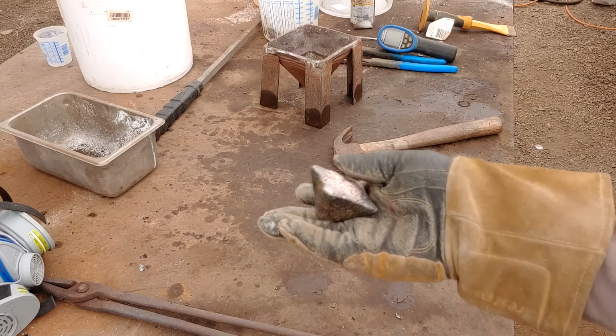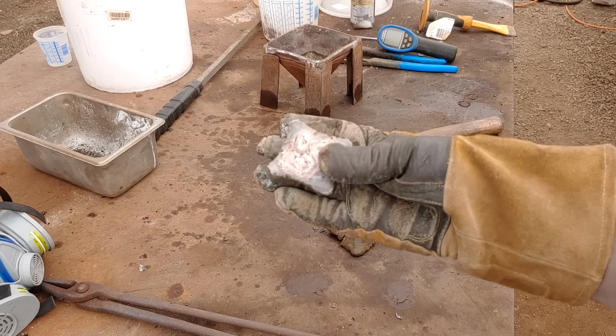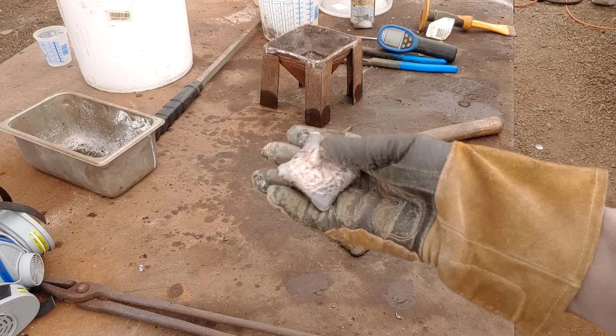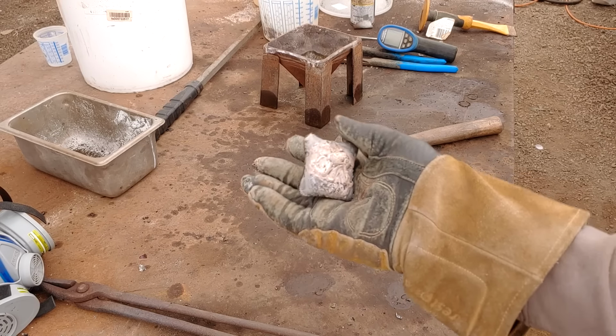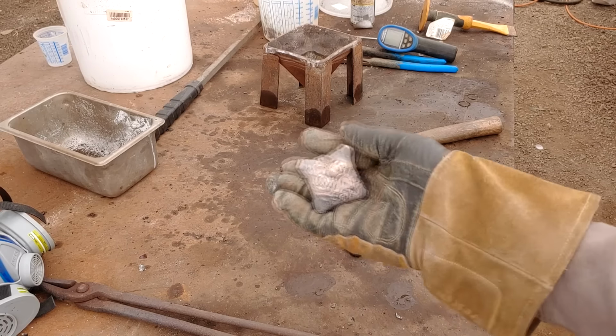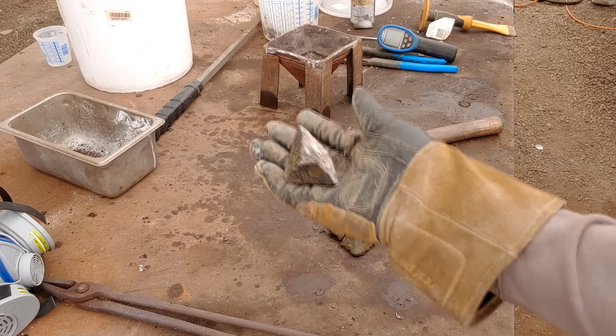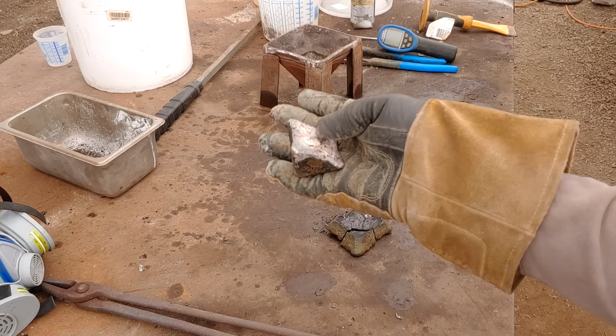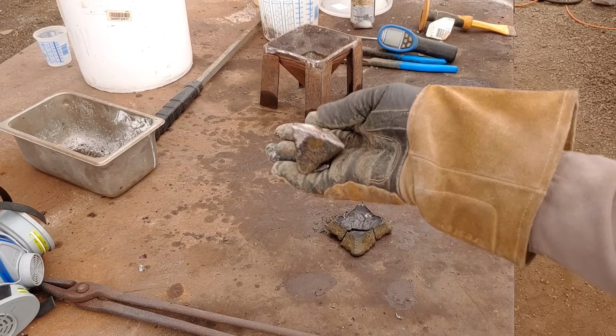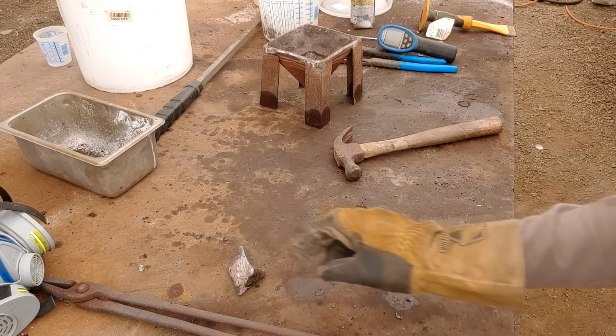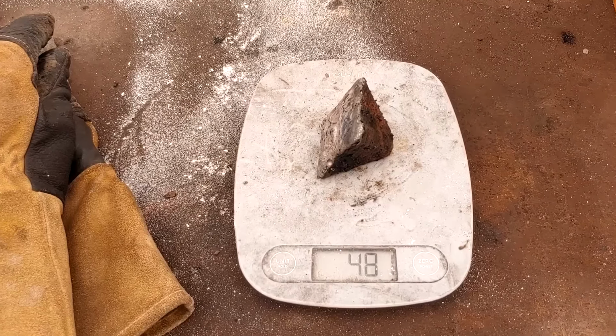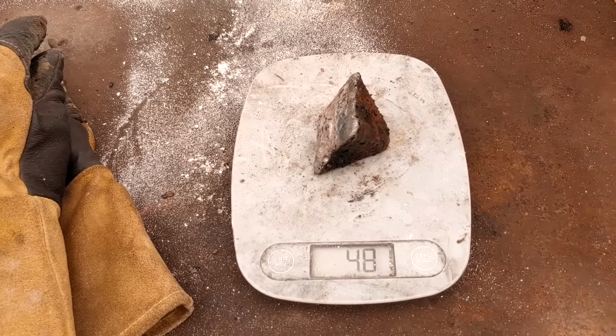But there is the metal, the oxides that we reduced from the slag by using iron. That worked pretty good. I'll get it cooled down and get a weight on it, but we reduced quite a bit of metal back out of that oxidized slag. And there we go. We recovered 48 grams worth of metal.